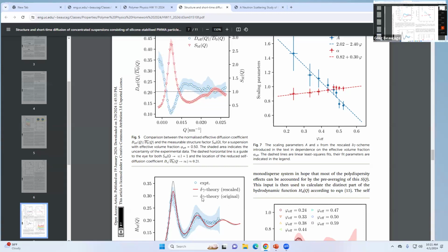It means the next order is either packing tighter or packing further apart. If it's smaller, it's packing closer. If it's larger, it's packing farther apart. That's probably more important than the amplitude. So basically, something's going on with the packing, and that happens to work out when he gets to one.